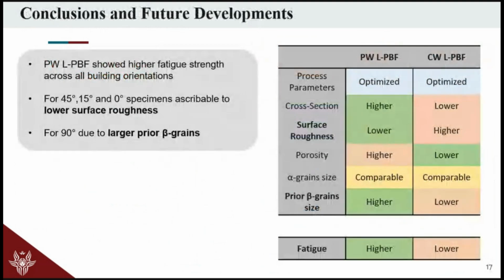At this point, basically, just to conclude, given two optimized process parameters, which are aimed at balancing the cost versus the overall quality, we can say that with this set of parameters, which doesn't mean that for every conditions we have that the pulsed wave is better than the continuous wave, but for this set of parameters, we have that generally at any building orientation, we have a better fatigue strength for pulsed wave due to a higher cross-section, a lower surface roughness, and also a prior beta grain size, which is higher. So the chance, statistically chance, to have localization of plastic strain at the boundaries is reduced.